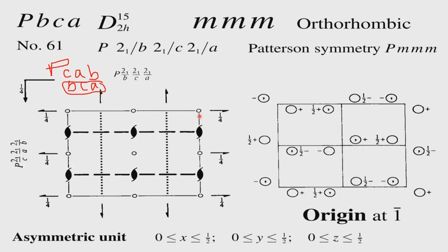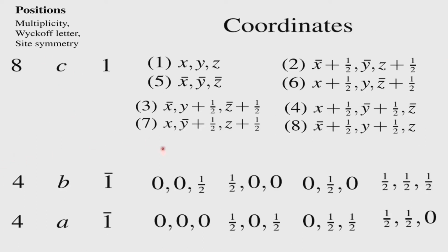That means, this framework is the lattice, and this lattice we can slide down in all 3 directions, and again we have the position of the center of symmetry fixed. And since the center of symmetry is a fixed position, we will have special positions when the atom or molecule or the system which we are discussing sits at the center of symmetric position. Okay, it is very clear, very simple, and therefore, you see now the special positions will be associated only with 1 bar. You have all the other symmetries, but only 1 bar is allowed.